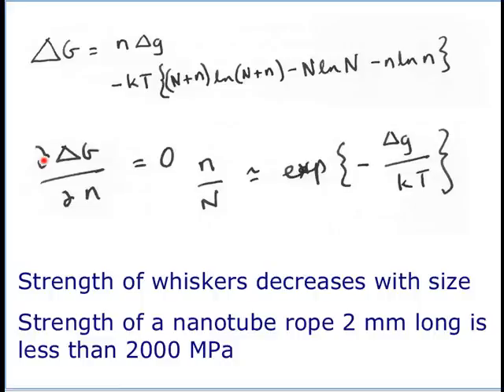And that is why all the research on nanotubes, which claims to have a material which will have a strength of 130 gigapascals, is complete nonsense. There is no nanotube rope which is longer than 2 millimeters, which exceeds the strength of steel. So just to summarize,